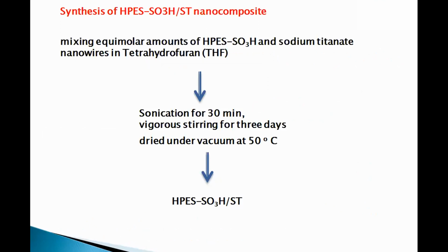The next step is synthesis of the hyperbranched ether sulfone with sodium titanate added to the polymer. This step is done by mixing equimolar amounts of hyperbranched ether sulfone and sodium titanate nanowires in tetrahydrofuran. This step runs under sonication for 30 minutes, with vigorous stirring for 3 days. Then the nanopowder is dried under vacuum at 50 degrees centigrade.